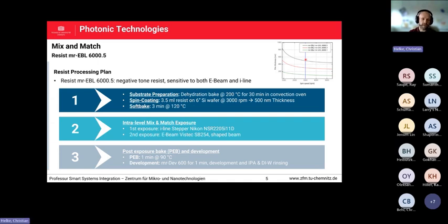Then after the photoresist is on the wafer, we have to expose the wafers. We started here with the I-line exposure itself because it's high throughput. And again, 25 wafers in, let's say, 30 minutes are done here. And then the whole batch of wafers goes to our E-beam tool in vacuum, where every wafer after each other can be exposed overnight or what else. After the exposure takes place, we have to use here a post-exposure bake at 90 degrees for 1 minute. And then we perform the development of the photoresist layer for 1 minute in MR-DEV 600, and then doing the rinsing in IPA and DI water.